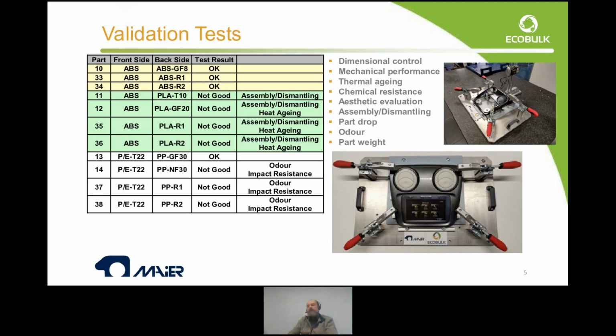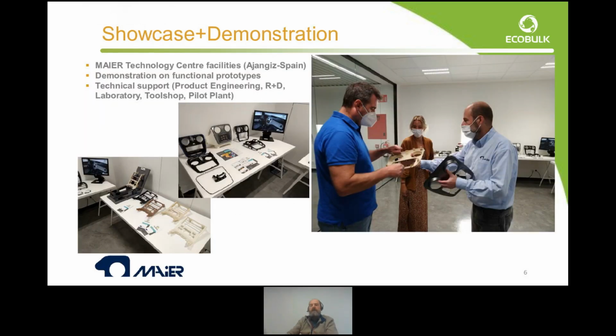In principle, we see that there's not so much difference from a conventional virgin prime material to a recycled one. We find more differences between an ABS, a PLA, or PP. So the idea is that the real performance of the component does not depend on the amount of recycled content, but on the kind of polymer we use to produce the compound. Let's go ahead.